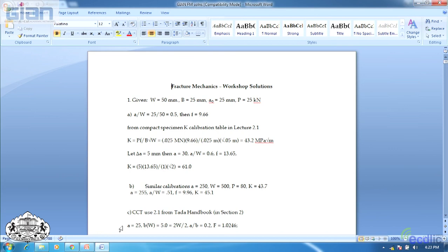Load is 25 kilonewtons, and remember the units are MPa root meters. So in order to do that, I put everything in meganewtons and meters. If you're real good with units, you can get away without doing that, but I have trouble. So I put everything in meganewtons. The little f is unitless. Then the thickness is 0.025 meters, and this is square root of 0.05 meters. I got 43.2. Now, if you didn't get that to start out, you ought to try it again, because that's what you should get.